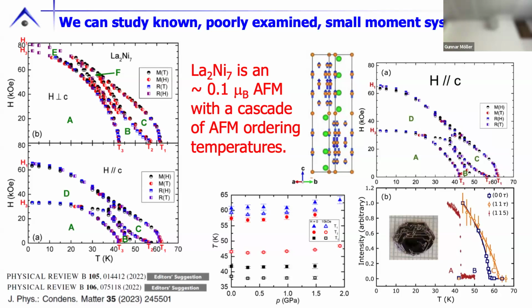And we started applying pressure. Now, we were doing measurements in the basal plane, and for that, we could see that we have very little pressure dependence. The two sets of data are showing that there's actually a larger field dependence than a pressure dependence, but this was only up to 2 GPa. We are currently measuring in diamond anvil cells with the current along the z-axis where we see better features, and we're starting to map out what happens there. So this one's still in play.